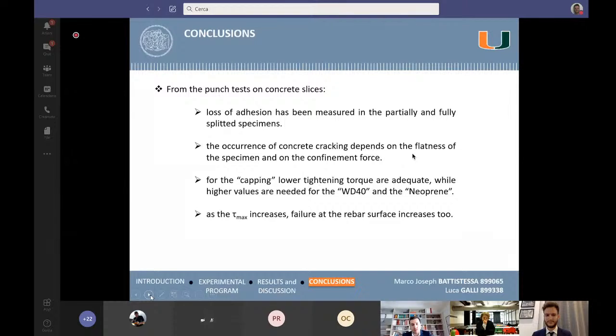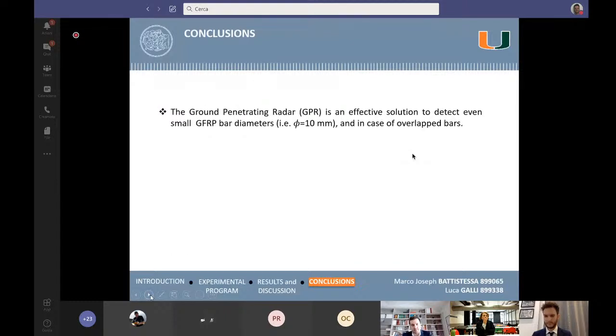In the visual analysis, it has been observed that a failure at the rebar surface is higher when the bond stress is also higher. But anyway, the most predominant failure mode has always been observed at the cementitious matrix level. The results compared with the ones of the previous thesis work have confirmed the reliability of the methodology proposed for the punch test. The ground penetrating radar proved to be an effective solution to detect even the small GFRP diameters, and also, as we have seen, in case of overlapped bars.